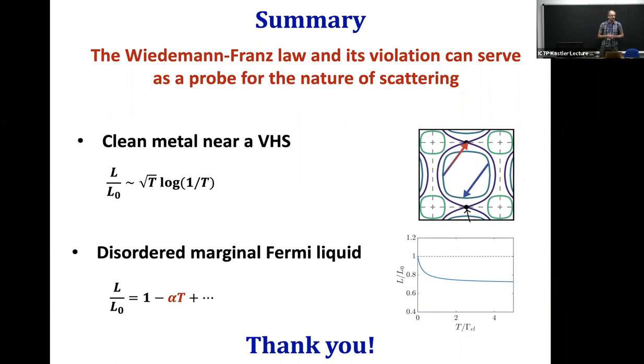So there's a question here. One last. Okay, so I understand that you have one minus alpha T, and then presumably minus beta T squared, minus gamma T cubed, etc. Yeah. But then the question is about the prefactors, because I'm guessing that alpha goes as one over W or one over W squared. Right? The prefactor itself will depend on the ratio between your disorder squared and your interaction, exactly. Right? Exactly. And so the question really would be, would the next orders, which come from phonons, completely dominate over this linear? Yeah. So in a clean metal, you would want to look at the relatively clean marginal Fermi liquid, and then the slope is very large. But it would also have to have weak electron-phonon coupling, which would also help. Which may or may not be the case.